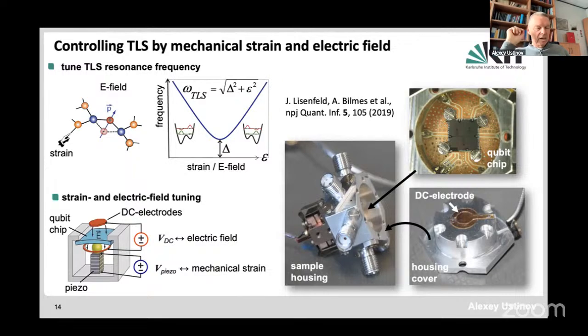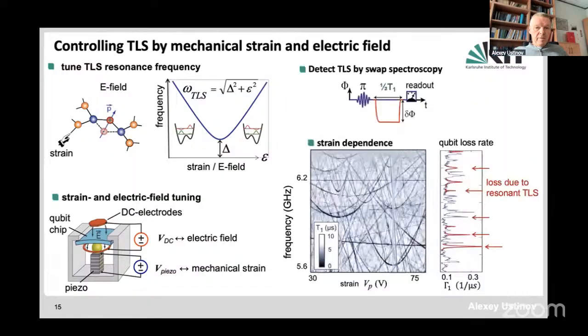We could also have done it with sapphire, but silicon is easier. And this bending introduces a variation of the flatness by the scale of a micrometer. But this leads to a deformation, which will be seen on the atomic scale in the range of 10 to the minus 7 or so. In this case, we are basically able to introduce some strain, and the strain may lead to a change of the electric properties of the circuit. And that's what we observe.